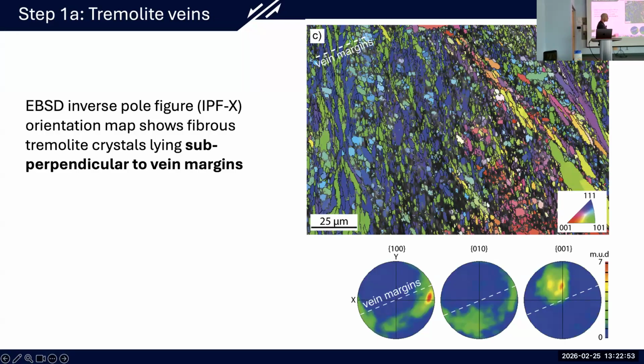So this image here is an inverse pole figure. This is the X direction. These colors tell you essentially how well-oriented a given crystal plane within our tremolite is to the X, the horizontal of this image. So if you see green, that means the 101 is well aligned to the X. Same applies to the 001 for the red, and the blue, the 111. And we'll reuse this scheme throughout. What we get from this is a very strong preferred crystallographic orientation where our tremolite crystals are subperpendicular to the vein margins. In the geological world, this is actually very common for any vein-forming context.